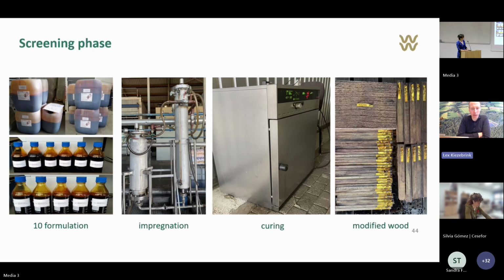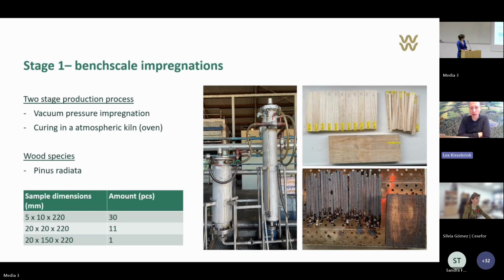The process itself is rather simple. We started with simple vacuum pressure impregnation. First, we apply a vacuum to suck the air out of the wood and make space for the impregnation solution. Then we apply a pressure of approximately 9 bars, and after that a vacuum phase again to make sure the samples do not leach that much anymore. After that, we cured the samples in an atmospheric oven at 130 degrees.